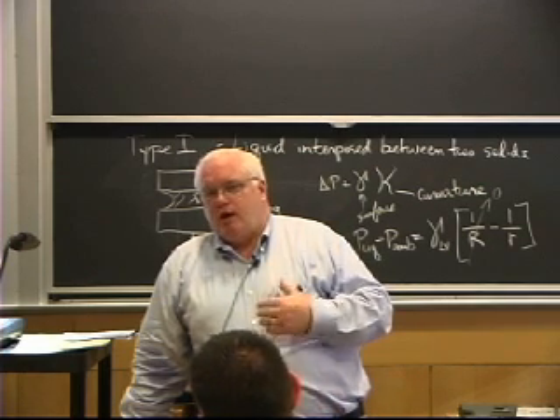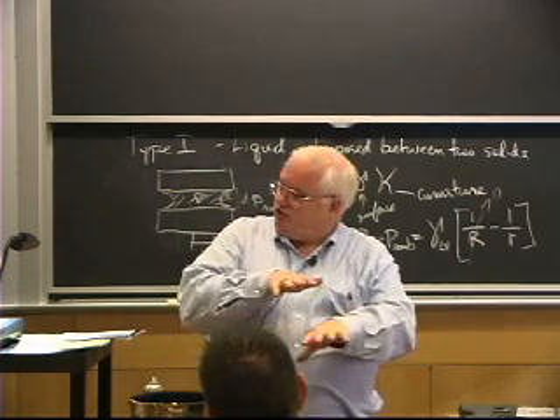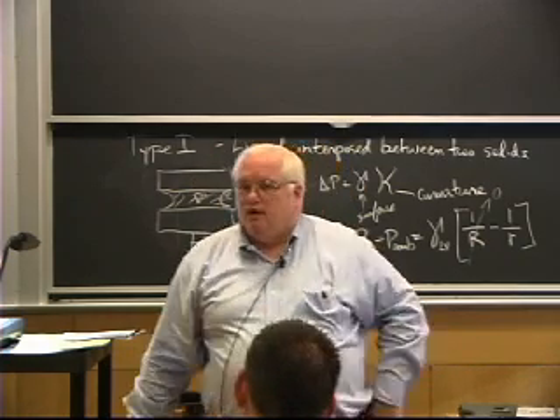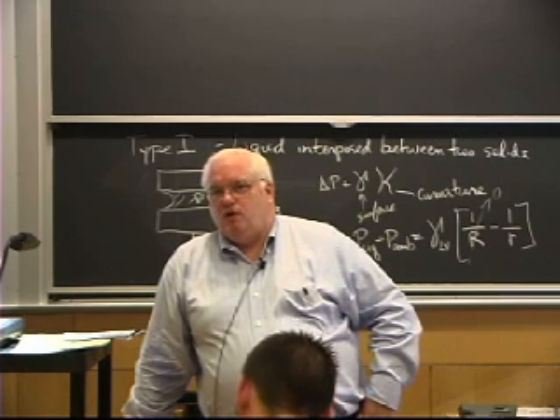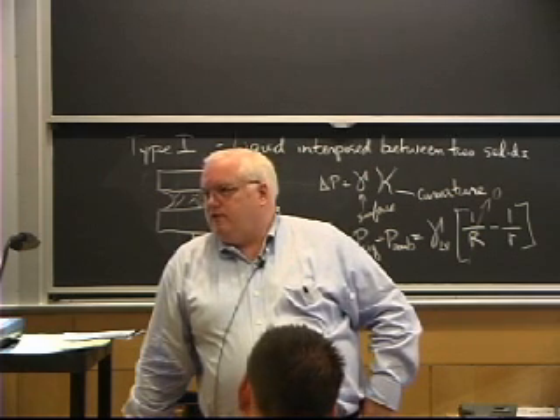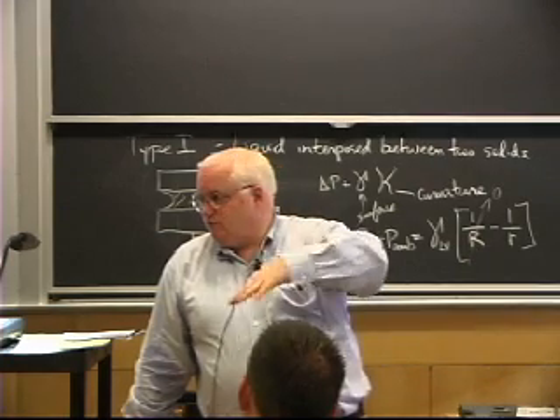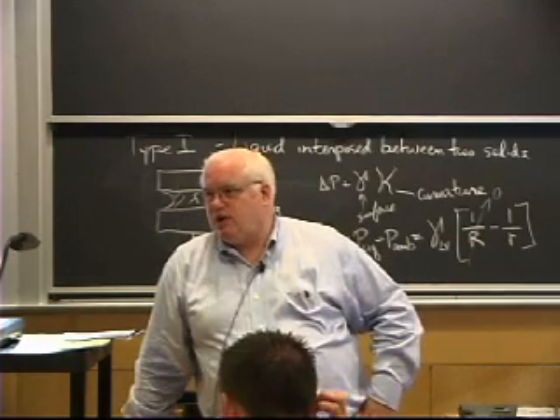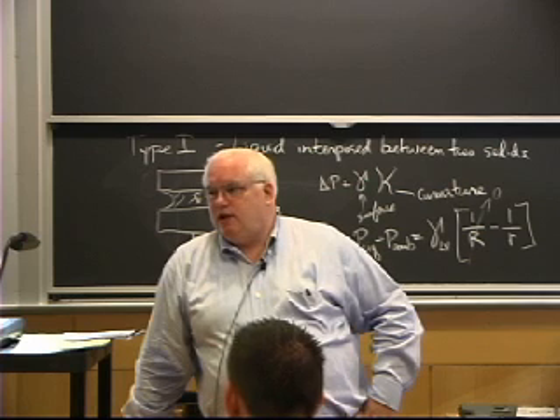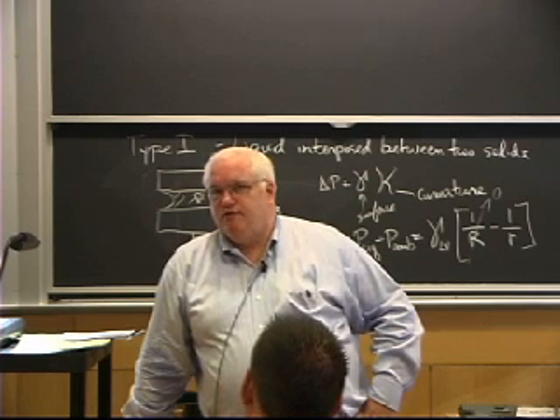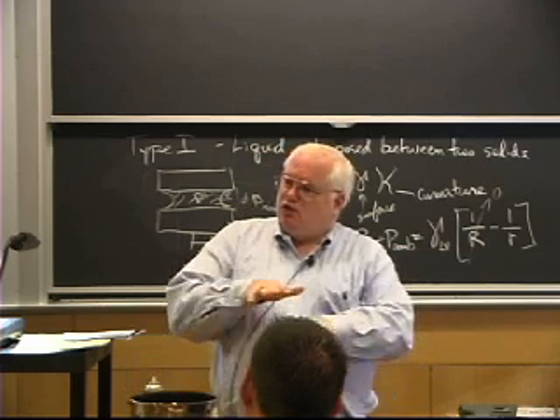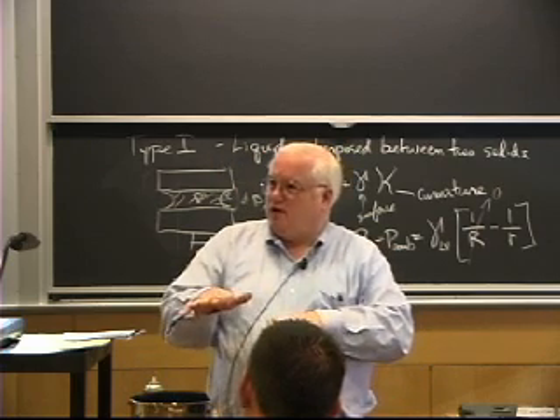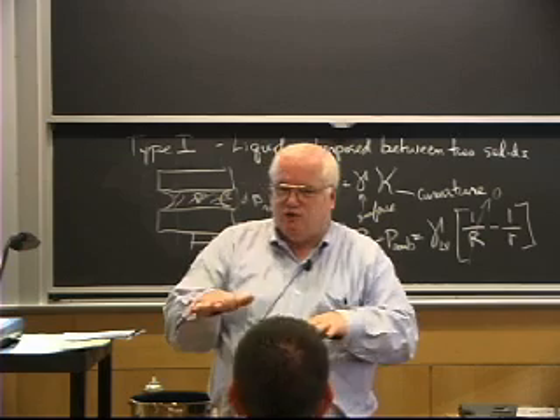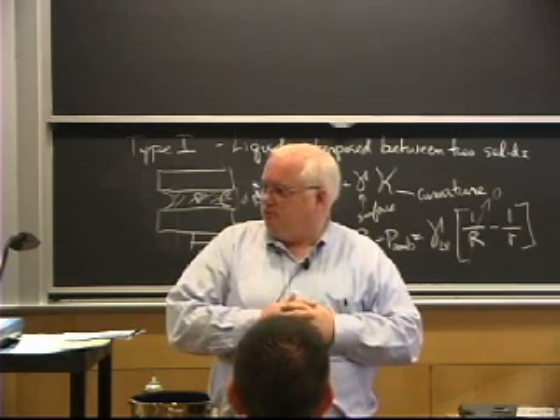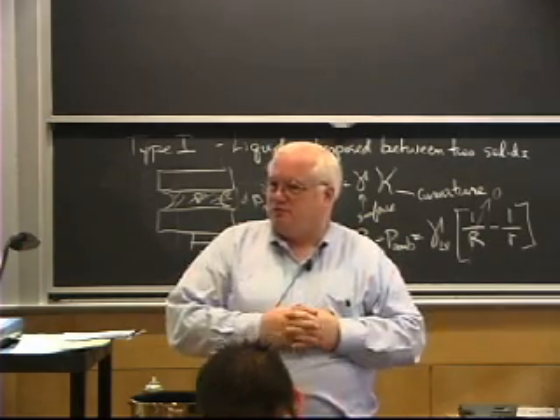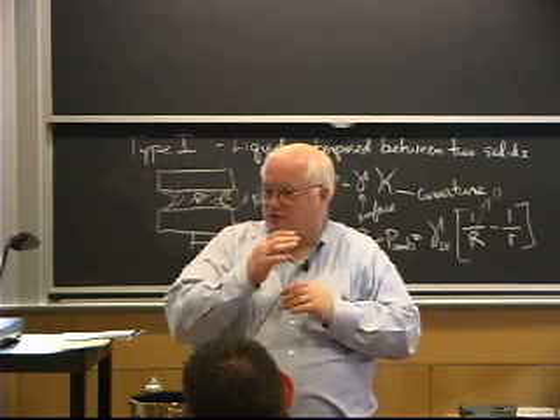A typical solid, anybody have an idea of what the viscosity, and viscosity is just the resistance to shear flow, right? A solid has a viscosity somewhere on the order of 10 to the 10th, 10 to the 15th. Professor Orowan, who was one of the founders of dislocations, once estimated the highest viscosity ever measured was 10 to the 22nd. And it happened to be the Finnish coastline. And he had to look at geological data in order to get his time constants. When you start getting to viscosities of 10 to the 22nd, you can't measure them in your lifetime. You have to measure them in millions of years to measure the flow of something like that.